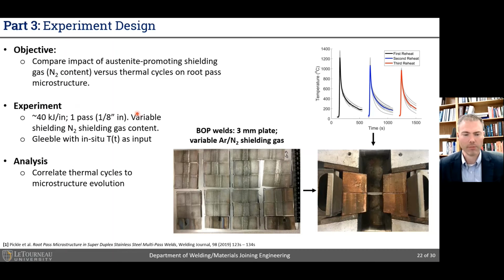So to understand the role that composition could play, we wanted to isolate the role of nitrogen stabilizing in these argon shielding gases. And so to do that, my students came up with the clever idea that we would make multiple bead-on-plate welds in 1/8 inch thick plate. So this is a single pass, penetrates all the way through the plate, but then vary and control the shielding gas content, and then use these for subsequent in situ reheating using the measured thermal response that we obtained in situ from the weld. And so now we can directly probe the degree to which composition is a factor as measured through the surrogate nitrogen content in these shielding gases as opposed to thermal cycle.